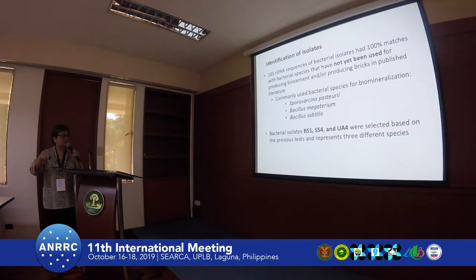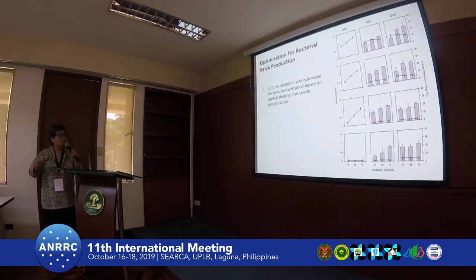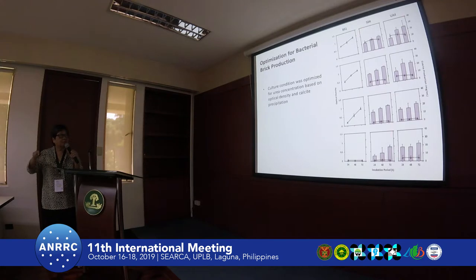So we then selected three isolates based on the characteristics that we tested, and these we optimized for bacterial brick formation. So in this figure, we show the three isolates and their optical density and their calcite production based on the amount of urea in the medium.